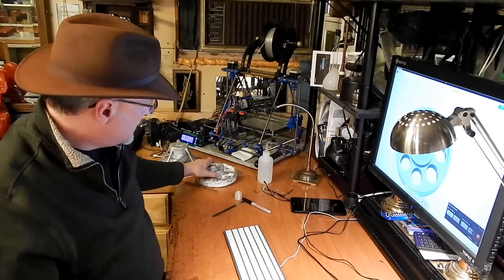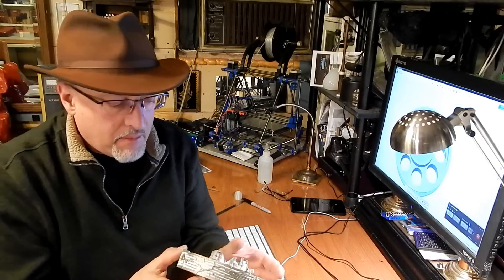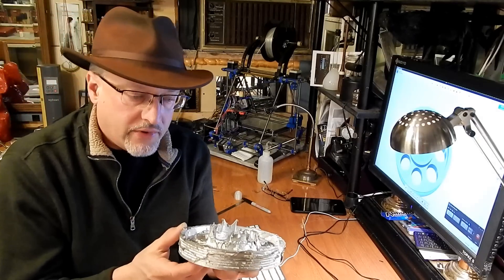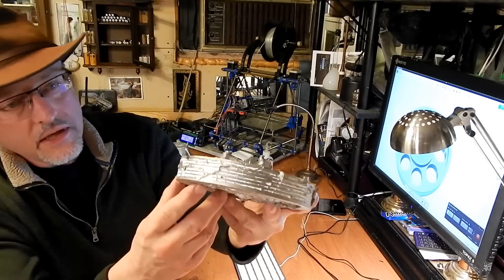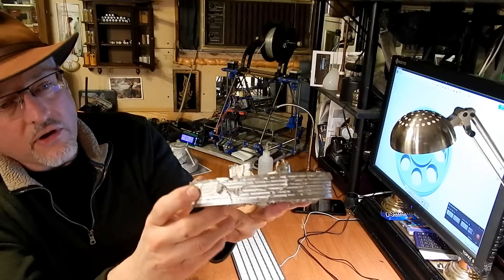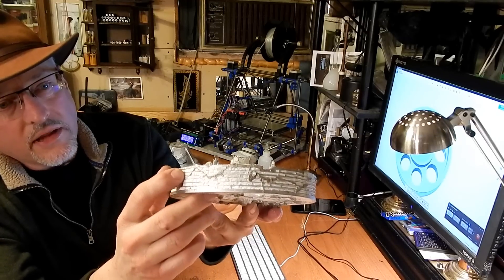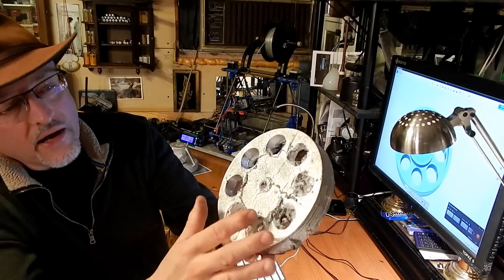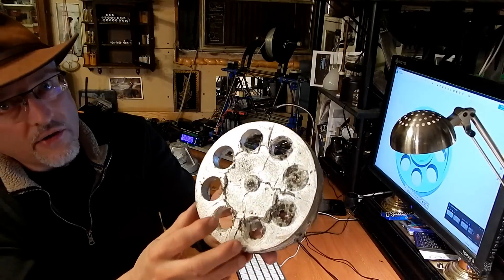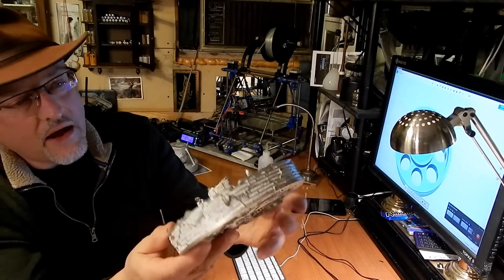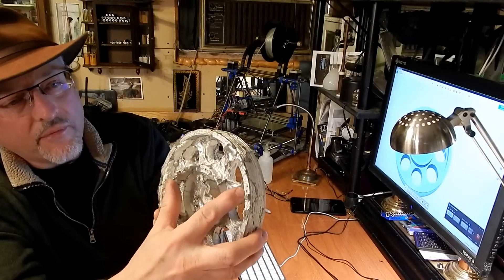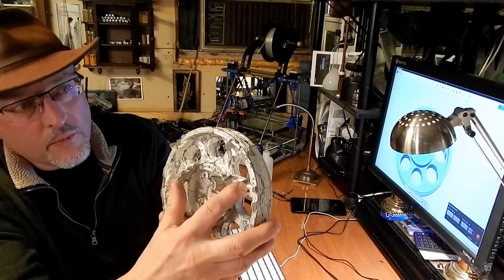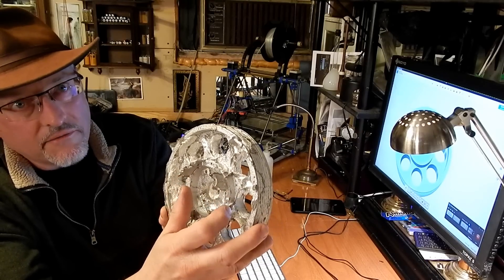And this is the part that I got out of it, but I got some cracking in the mold and you can see the cracks around the edge and some cracks in the bottom. And that caused the aluminum to leak out. So I have some hollows where the aluminum wasn't completely full.